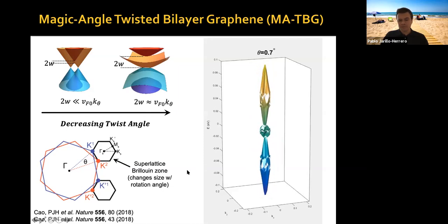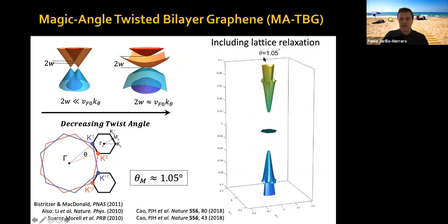So you take a snapshot of this at about 1.05 degrees, and these simulations include lattice relaxation, you can see that there is this very flat band, okay? When you have a very flat band, that means your kinetic energy is quenched, and therefore the Coulomb interactions between your electrons acquire disproportionate importance.